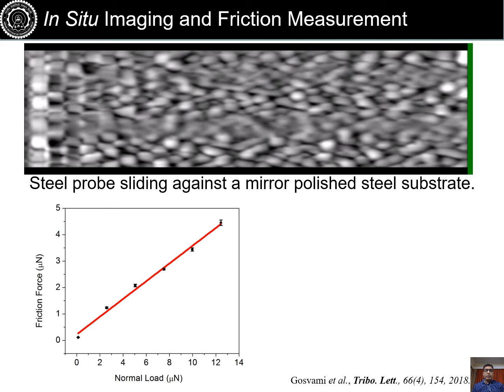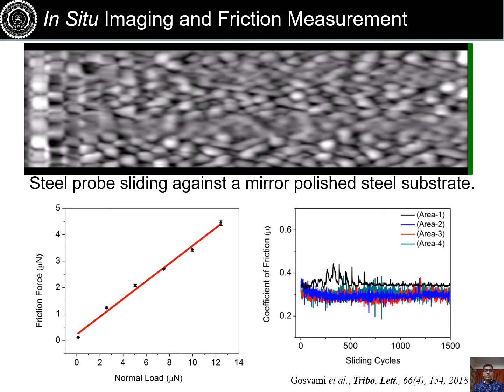And one more advantage of using this microsphere against a flat surface was that we see that friction force is proportional to normal load, and from there we can calculate the coefficient of friction, which makes this tool more similar to a tribometer, which people use for macro scale friction, wear and lubrication experiments. So the major advantage is that you can also have a variety of probe material which can be used in the form of microsphere attached to the commercial AFM cantilevers, and then you can study a variety of tribo pairs.